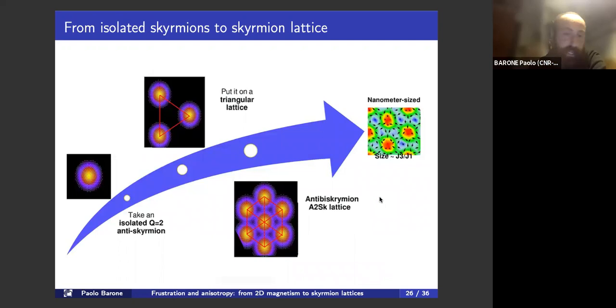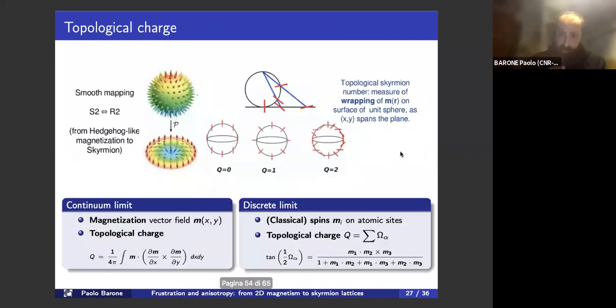And the idea is that we can imagine starting from an isolated anti-skyrmion, putting it on a triangular lattice, and then squeezing the lattice until in the end we end up with a spin texture which is very reminiscent of the one we found in our Monte Carlo simulation. Of course, we can provide a better characterization of such a topological phase.